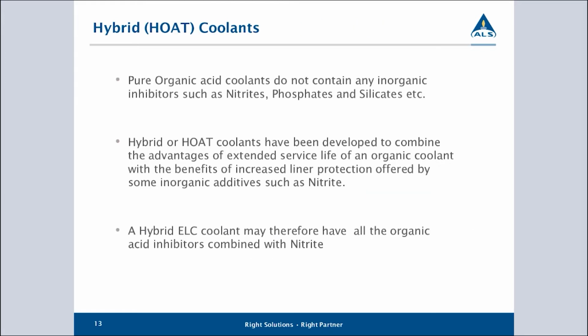The hybrid coolants are literally a mixture of organic acids and one or more of the sacrificial type inhibitor additives. And the most common one you will find in there is sodium nitrite. This is particularly common if the coolant is intended to be used on an engine that's got cast iron cylinder heads, cast iron blocks. There are other inhibitors that will be used if we're dealing principally with aluminium components. Sodium nitrite is not very good at protecting aluminium, particularly at higher concentrations. It can become problematic to the system, which kind of suggests that we need to be careful as to what coolant we're using in what system to make sure that they are compatible with each other.